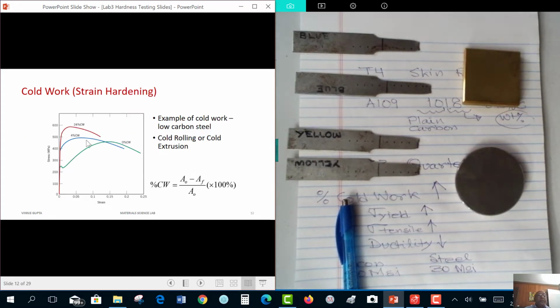So here is, for example, cold working of low carbon steel. So these are the results from cold rolling or cold extrusion, where you start with a large area and you reduce the area by extrusion or rolling. So we define our percent cold work by this percent reduction in area. So now you can see why I mentioned that ductility expressed in the form of percentage reduction in area is a better measure.